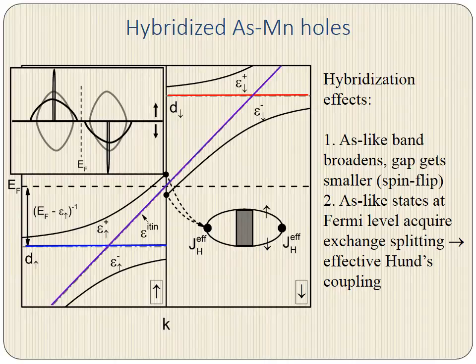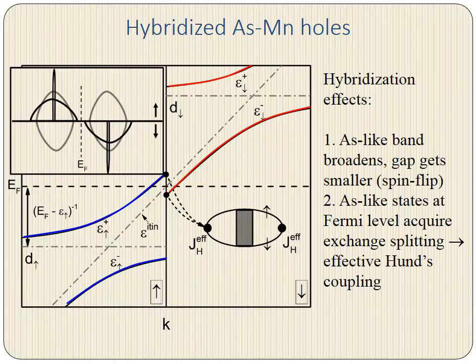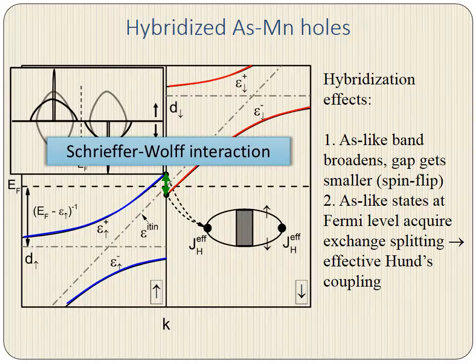Crossing these bands is an unpolarized arsenic-like band. So what we'll do is we'll allow that arsenic band to hybridize with the manganese, which, as we recall, will broaden the overall band. More importantly, this will lead to a polarization of the arsenic-like holes at the Fermi level. Now, this interaction we just described, where the holes and moments are of a different species, is also called the Schrieffer-Wolff interaction, and it was originally put forth in the context of Kondo theory.